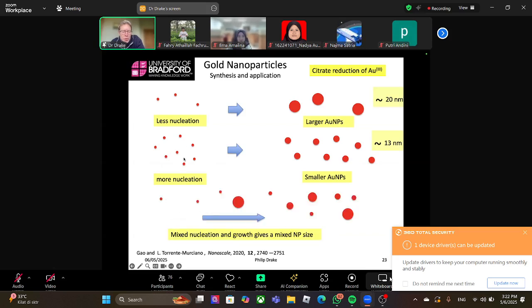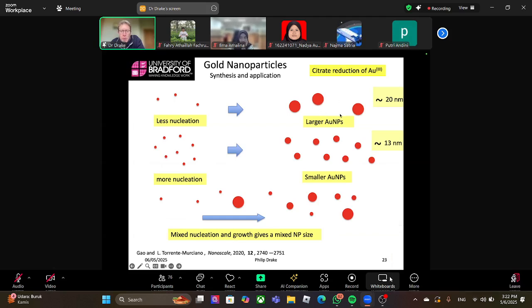If we have uncontrolled nucleation, so nucleation and growth all happening at the same time, we get a nucleation site that grows to a nanoparticle, with more nucleation sites, more growth, and you get a mixture of different particle sizes. So the best way to get homogeneous particles is to have controlled rapid nucleation followed by controlled growth. If you get heterogeneous particles, a very big size distribution, it is when you have growth and nucleation all occurring at the same time.